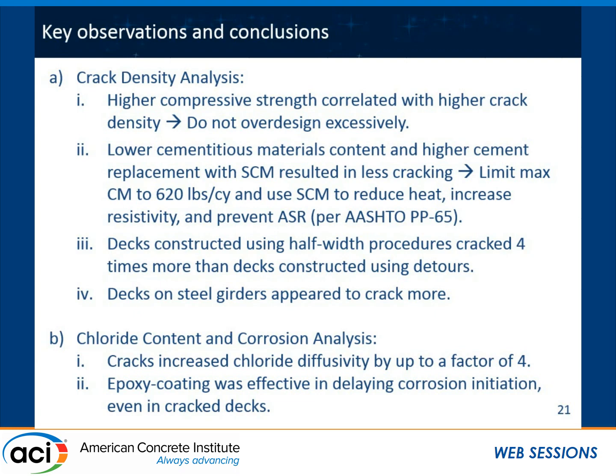So on the diffusivity front, we figured out that what's really important is the total volume fraction of the cracks as opposed to the width of the cracks. The volume fraction in this work would translate into crack density. How many cracks you have per unit volume or unit surface of your deck makes a lot more impact than how thick your crack is, essentially because there are not a lot of surface effects in play, meaning that the surface of the crack cannot slow down the movement of chlorides significantly.